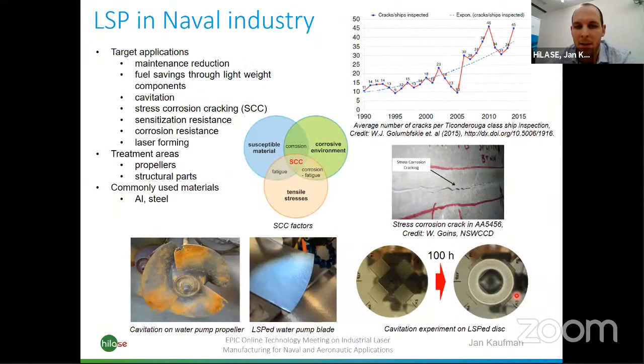When it comes to LSP in the naval industry, the philosophy here is to basically reduce maintenance costs, reduce maintenance in itself, and also reach some fuel savings through lightweight structures. When you have more lightweight materials, you tend to reduce the material, and some of these joints become weaker, and that's where you can use LSP to strengthen them in these critical areas. Over here, we can see a graph which tells you the number of stress corrosion cracks over the course of 25 years on this Ticonderoga class ship. And you can see that since 1990, the number of cracks per inspection has been steadily increasing. We can assume this problem is going to increase even more. So this problem is not going to go away. It's going to be more and more urgent.